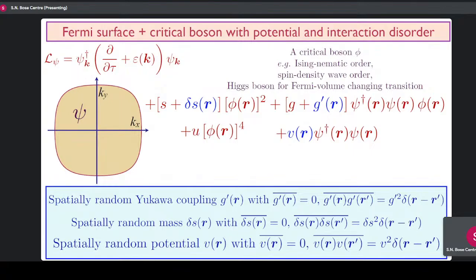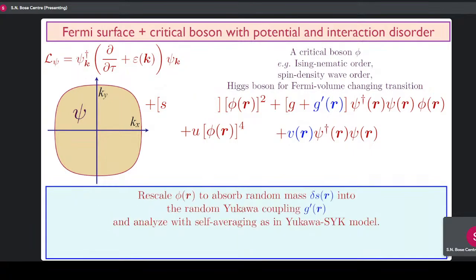But now we realize what we can do with this theory, at least with the terms written: I can just rescale phi so that this becomes a constant. And then it will introduce disorder in other terms, like this term here, but maybe that's not as important. That's what the argument will tell you. But what it will do is change the disorder here. So we rescale phi to absorb the random mass, and then this random coupling becomes strong.